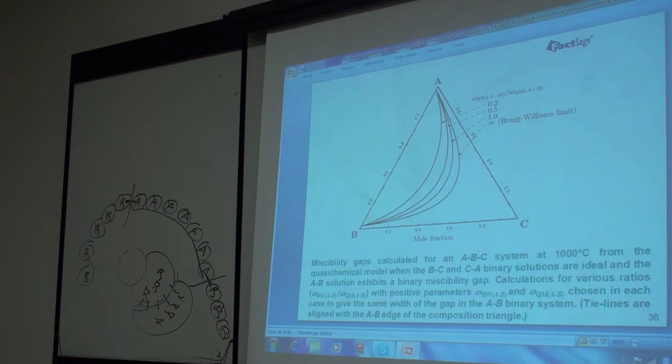However, we're writing up a couple of papers on it. Supposed to have been writing one up for the last year. Showing, however, that in a series of systems, you can find pretty much a trend. So you take a whole pile of systems and you use the same ratio in all the systems, pretty much, or you use the same value of Z for all those systems. So it isn't quite as bad as it looks. You don't have to guess every system. Generally, if we get the right value of omega, either the ratio or the value of Z that we use that gives you the best fit in the binary, it also gives you the best fit out here.